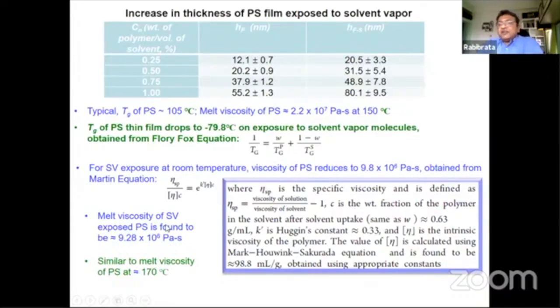It's completely contrary to the general belief we had that solvent vapor exposed films have a drastic drop in viscosity. In fact, it is very close, and only at 170°C instead of 150°C, if you heat the film at 170°C thermal annealing, the viscosities match identically. We did that as control experiments also, and we saw that for the thermally annealed sample, the timeline was very, very long, even at 170°C. So the first thing that we realized is reduction of viscosity is not responsible for this ultra-fast dynamics.